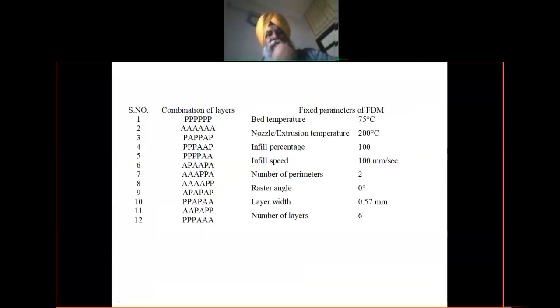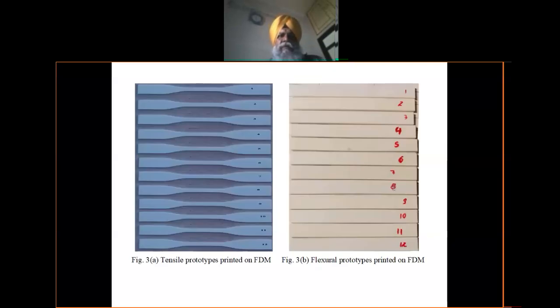What we did is we performed some random experiments in which the materials were printed in different layers, with the bed temperature at 75 degrees, nozzle temperature 200, and infill percentage, infill speed, number of perimeters, raster angle, layer width, and number of layers all kept fixed, right? So we printed different numbers of layers. Once I have all the layers of a single material, let us say all 6 layers of PLA, all 6 layers of ABS, then at random we selected PLA on ABS, then ABS on PLA, and tried some different combinations to see what the effect on the mechanical properties is if I have multi-material printing for this type of substrate material. You can see the different types of tensile and flexural samples. We tried to measure their peak load, peak elongation, break load, break elongation, peak strength, these types of properties.